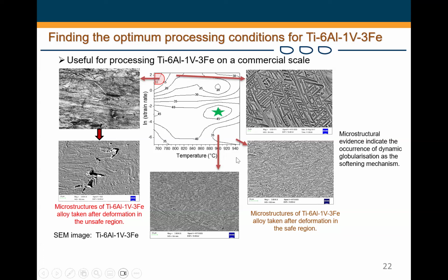these parameters, deforming at temperatures around 900 and 950, and reducing the deformation speed to about 0.1 to 0.01 per second. But this is presented as a log of strain rate. That's why it's different. If you do the conversion, it's more or less 0.01 to 0.1 per second strain rate. Within those regions, you can begin to have those rounded structures, and that is really good for processing of titanium alloys into different shapes that you would like it to be.